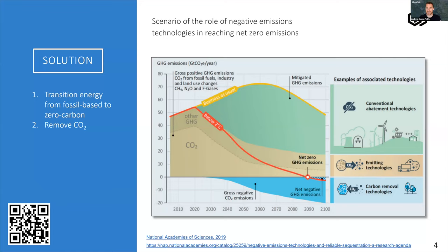If you take that yellow region in the middle there, you usually let woody materials react for tens of minutes to an hour or plus. What we know, based on the kinetics of heat transfer and reaction, is that it's possible to get this down to much lower timescales, an order of magnitude faster. Now, if you can go 10 times faster, that means you can process 10 times the amount of material through the same reactor, and that drives down the capital cost and the operating cost dramatically.